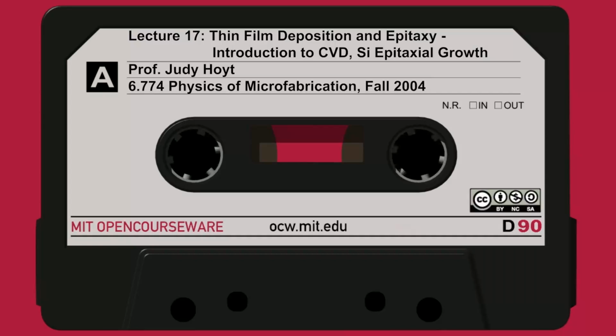And there are a couple different curves here. So here's the curve for silicon tetrachloride. Silicon tet doesn't react very well at low temperatures, so its growth rate is relatively slow compared to trichlorosilane, dichlorosilane, which is SiH2Cl2, that's dichlorosilane, very commonly used today, or silane. Silane's the most reactive of all these, and so at any given temperature it has a higher growth rate. You can see that. But look at the shapes of the curves.